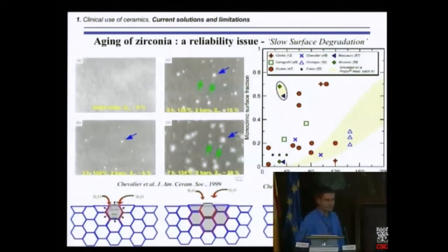And then, step by step, with time, there is an increase of the size of these spots, and the number of sites increases also with time. So this is a kind of nucleation and growth mechanism in which the monoclinic phase is progressively invading all the surface of the zirconia. This is after 3, 5, 7 hours in autoclave. We did this on zirconia femoral heads in '99, so that's quite a long time. And people said it should be no problem in vivo because you are working at 134 degrees C, so much higher than the in vivo situation.